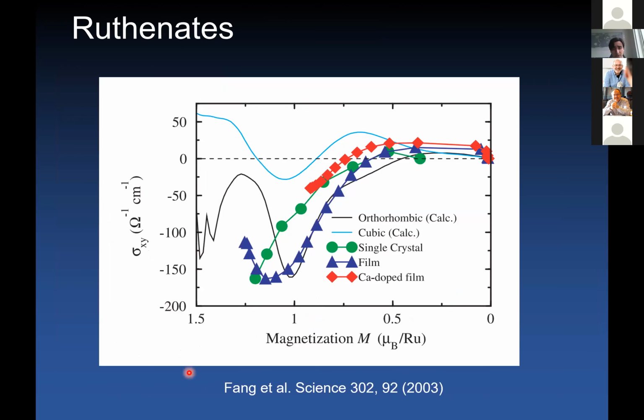This has been studied. So this is a proposal that came already in 2003. And here in this particular paper, the topological structure that was discussed for strontium ruthenate in the bulk was essentially a single source of Berry curvature at the gamma point that was dubbed here as a magnetic monopole. And this was used to understand the evolution in magnetization and temperature of the anomalous Hall effect in this system. So the ruthenate displays a very unusual change from a positive to a negative anomalous Hall effect that finds its explanation in this band topology.